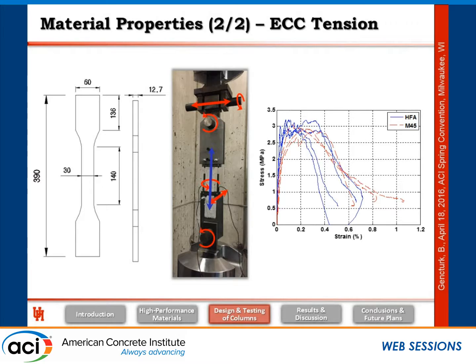These are the results that we got from the larger batches of ECC. If you prepare small lab mixes, it's much easier to control the strains. But if you want to make really structural scale mixes, more than, I would say, 3-4 cubic feet, then it's very difficult to control the properties of ECC. And this is also documented in the literature. So what we got for these columns wasn't what you would maybe commonly see in literature for ECC. We got about 0.5% strain. This is still like 50 times more than what you would see in concrete, but still, it's not as high as we would expect. So we're working on it to see how we can make ECC go to higher ultimate strains when we produce it at a larger scale.